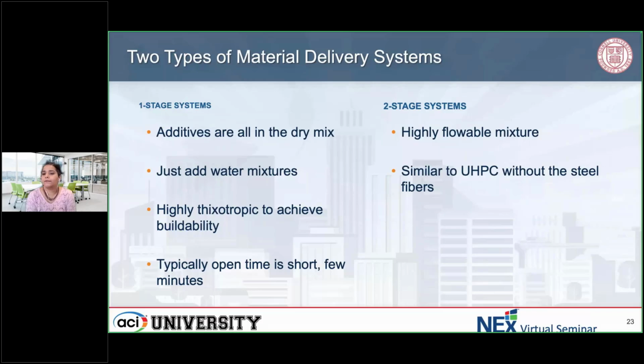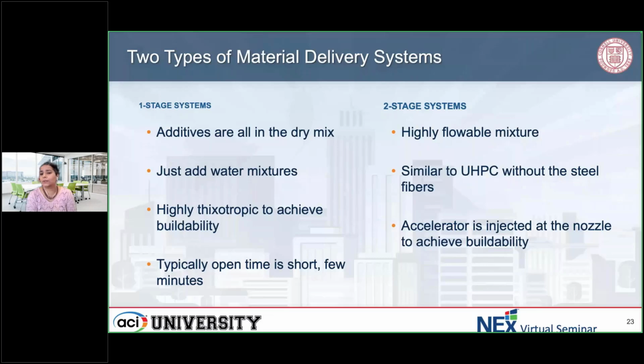So in our case, because we have a very flowable mixture, we inject an accelerator at the nozzle. This is what makes it two stages. The first stage is mixing and pumping it, and the second stage is the addition of the accelerator, such that once the accelerator starts working, as a chemical additive, you can achieve buildability. And you can typically have longer open times, but this is from the flowable mixture perspective. Once you add the accelerator, though, it's very close to the nozzle, and you want to be able to print right away. So the open time is for the flowable part till it gets to the accelerator.